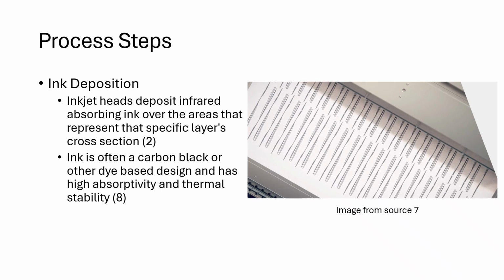Next, an inkjet printhead selectively deposits the radiation-absorbing ink onto the layer's cross-section. This printed pattern defines exactly which regions will fuse in the next step. The ink is usually carbon black based or another similar dye that easily absorbs infrared radiation and stays stable at elevated temperatures. The printheads are usually some form of piezoelectric inkjet technology. The particulates inside the ink are sometimes referred to as radiation-absorbing materials, or RAM in literature.